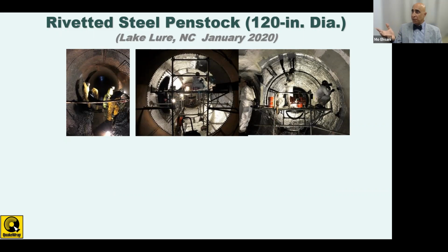By the way, as you notice, because these pipes are so large in diameter, they allow man entry. So our crew would enter into the pipe typically from an existing access hatch or manhole. Once they get inside of the pipe and the pipe is clean, then these layers of carbon and glass fabric are applied to the surface of the pipe. Again, if it is a steel pipe, we begin with the first layer of glass, and then on top of that, we apply the layers of carbon.